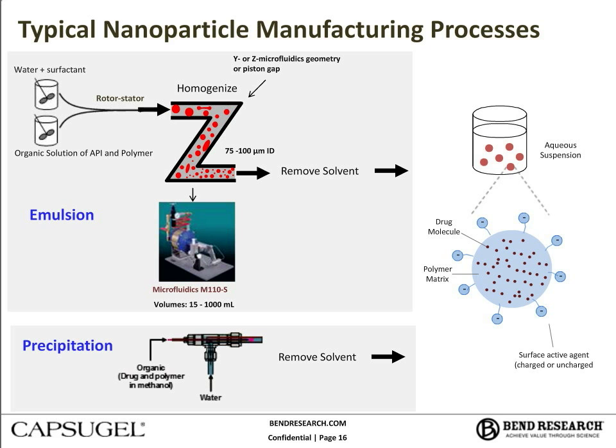So I'll move from nanocrystalline suspensions to amorphous drug polymer suspensions. These nanoparticles consist of drug molecularly dispersed in a water-insoluble polymer matrix, usually using a stabilizer such as a small molecule surfactant. High glass transition polymers such as cellulosics or acrylates are normally used to help maintain physical stability in the amorphous state. I'll describe a couple of the commonly used processes, although there can be quite a few variations, and I won't try to cover every possibility.